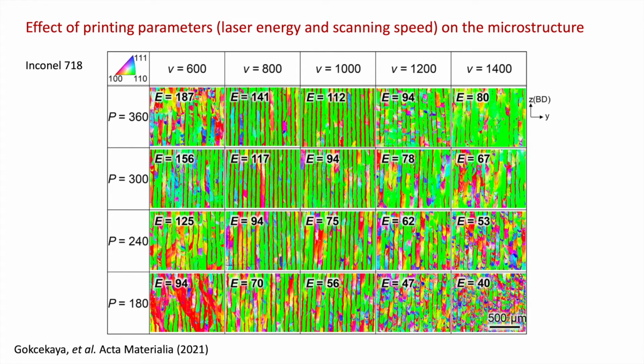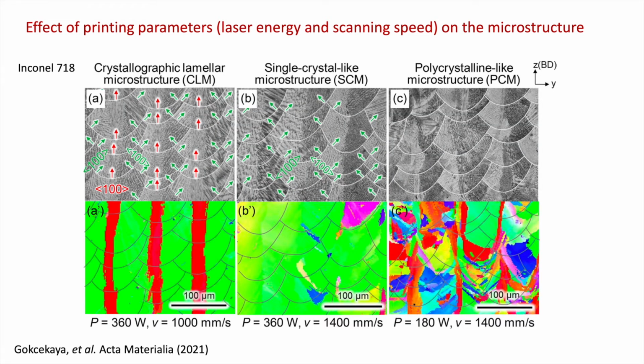Why is this the case? To answer that, we need to come back to the theory of solidification. When solidification happens, the grains don't grow randomly. There's a preferred growth direction. That's the 001 direction for FCC metals. During 3D printing, a lot of melt pools are created. These 001 grains solidify, then grow normal to the melt pool.